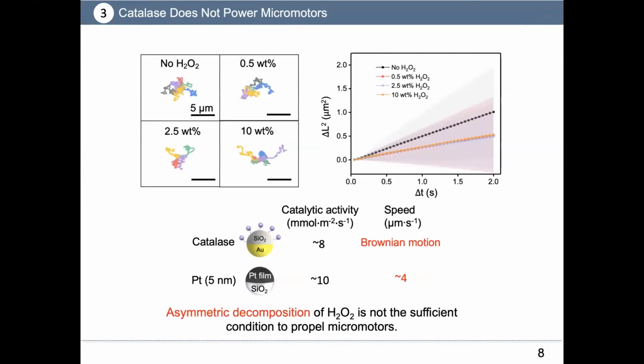Similarly, by measuring the amount of oxygen bubbles, catalase is comparable to platinum in its catalytic performance. However, its trajectories and mean square displacement data show that the silica catalase Janus microsphere just exhibits Brownian motion. Based on the above experimental phenomena, we believe that the asymmetric decomposition of hydrogen peroxide is not a sufficient condition to propel micromotors.